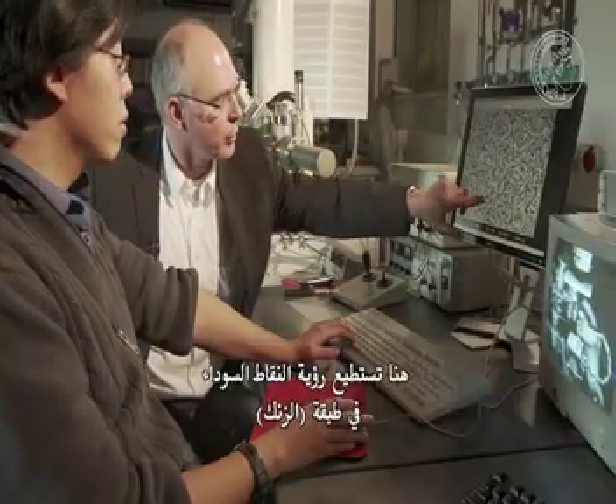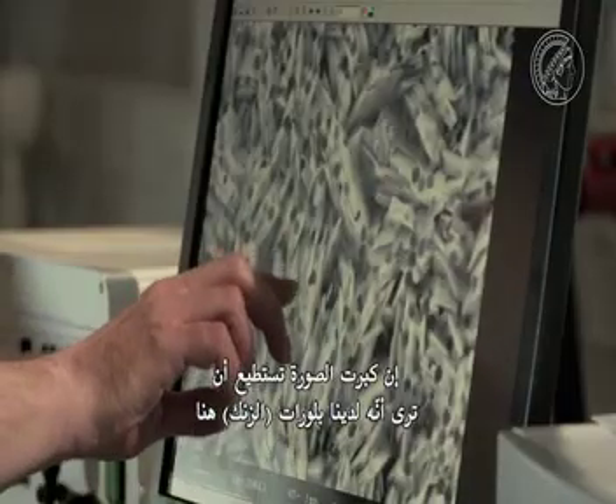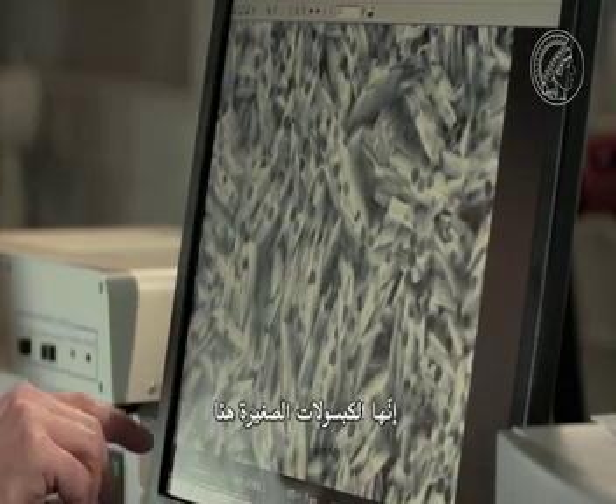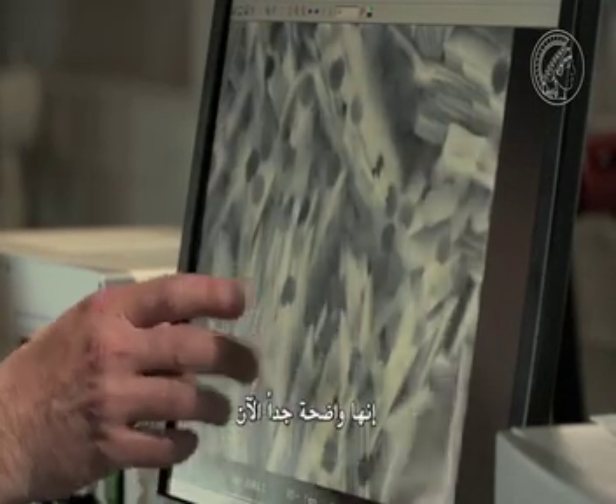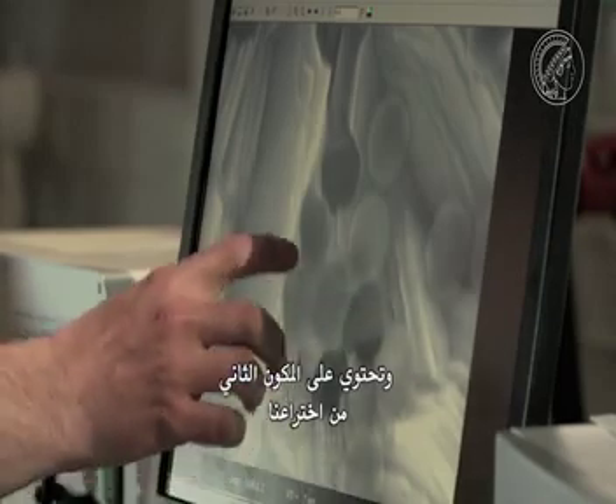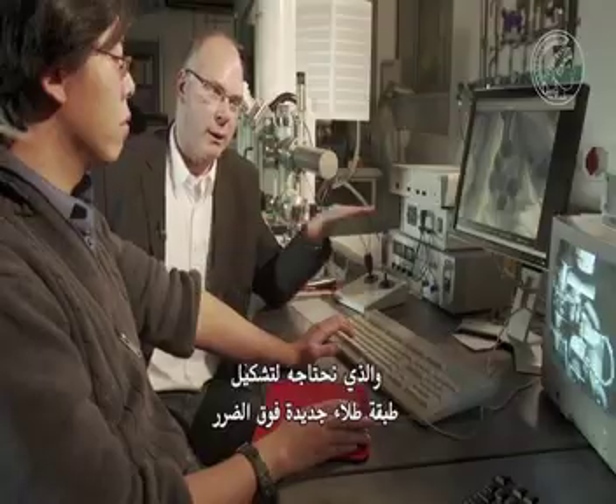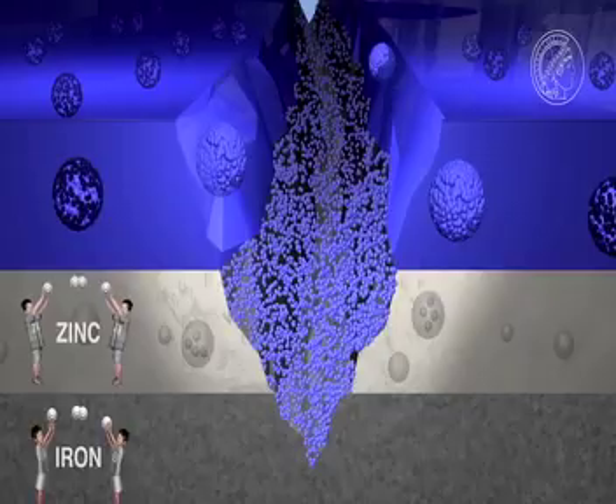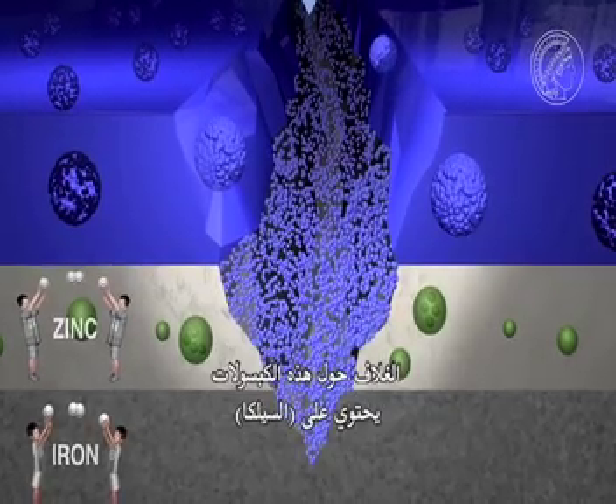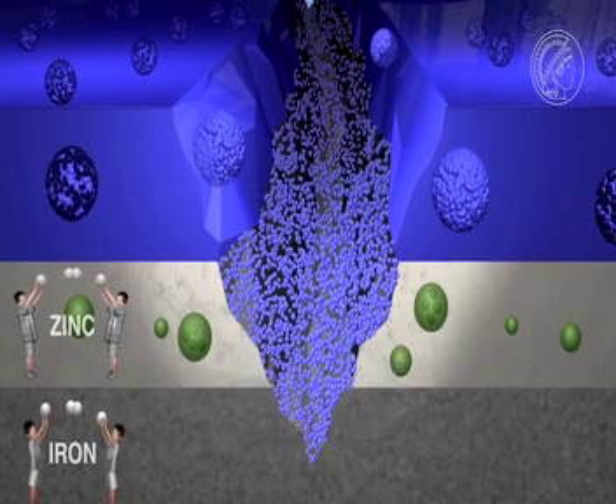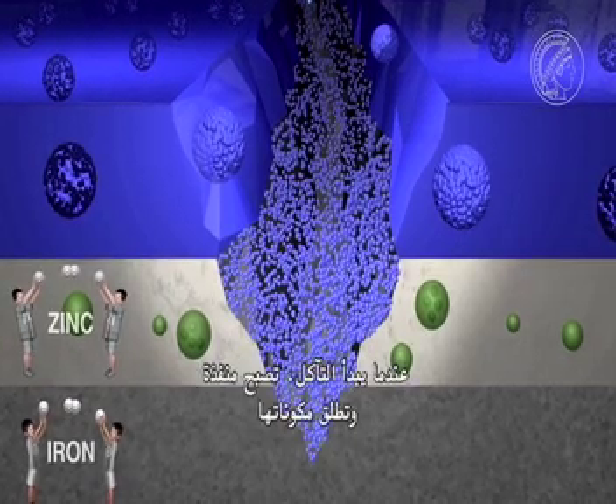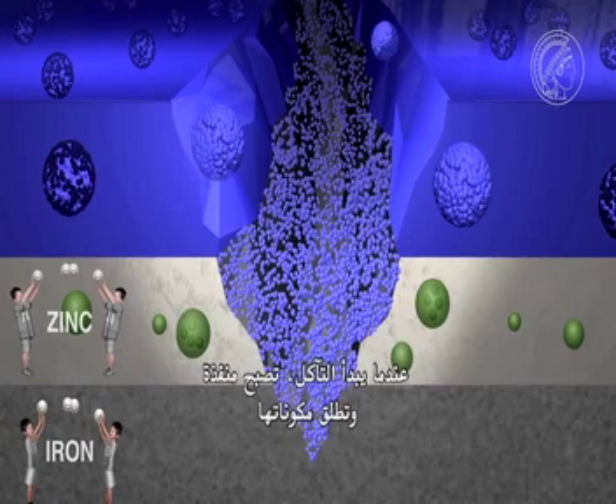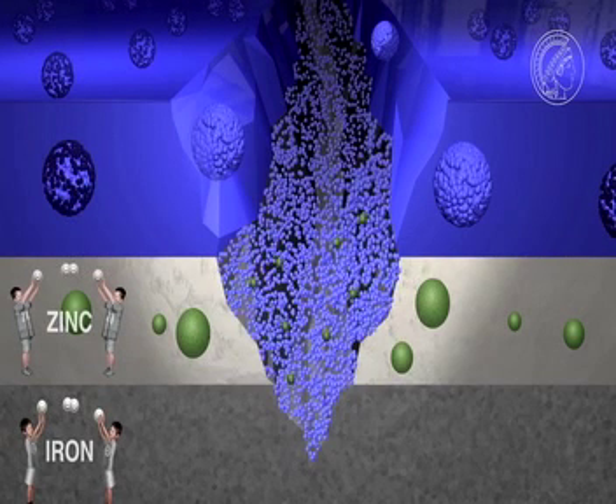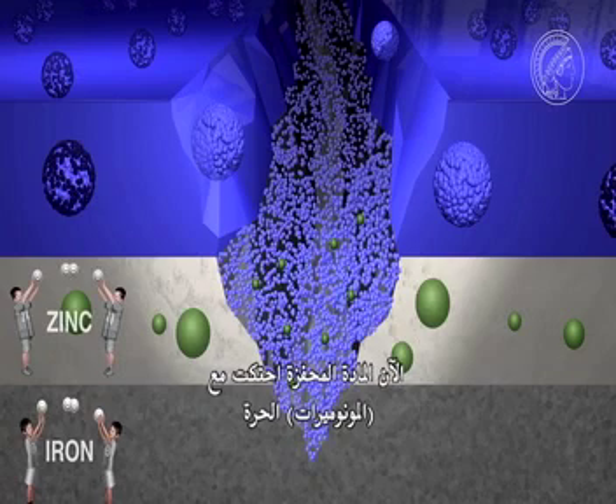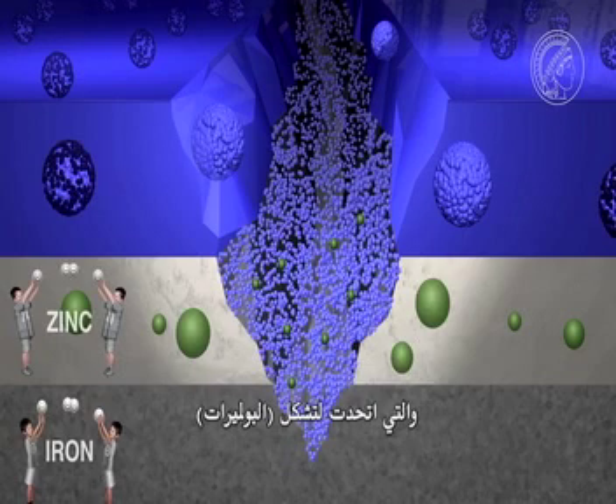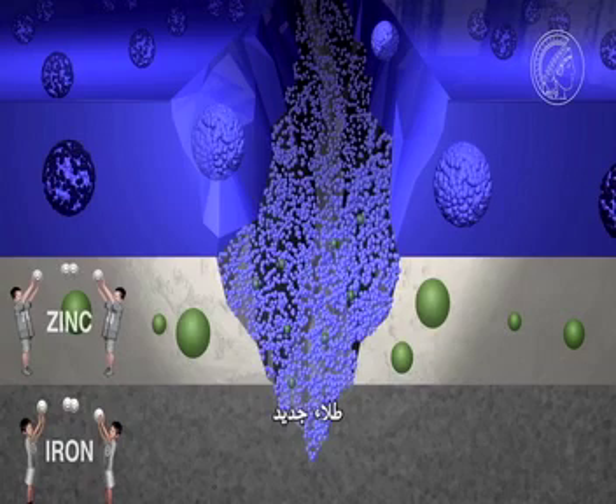Here you can see the black dots in the zinc layer. If you zoom in here, you can see quite clearly that here we have the zinc crystals. They are little capsules here. And now they are clearly visible and contain the second component of our invention, which we need to form a new layer of varnish over a defect. The casing around these depot capsules consists of silicon dioxide. When the corrosion begins, they become permeable and release their contents. Now the catalyst comes into contact with the free monomers, which combine to form polymers, a new varnish.